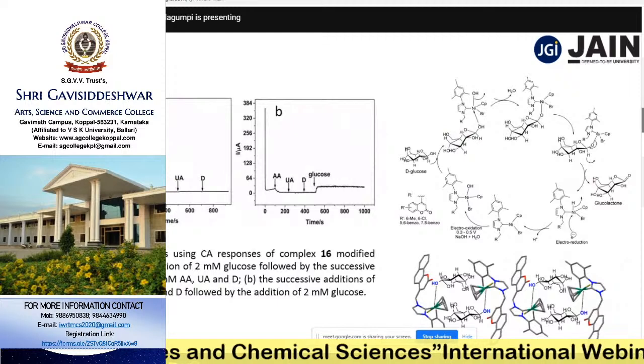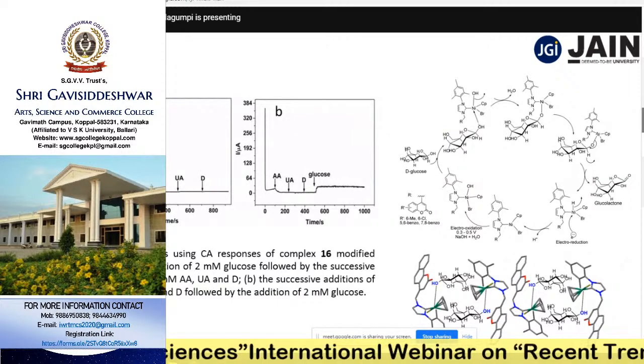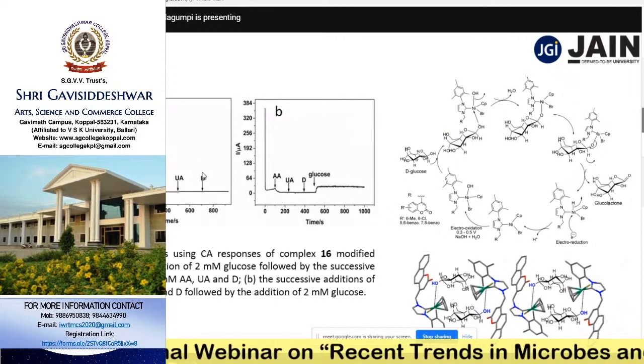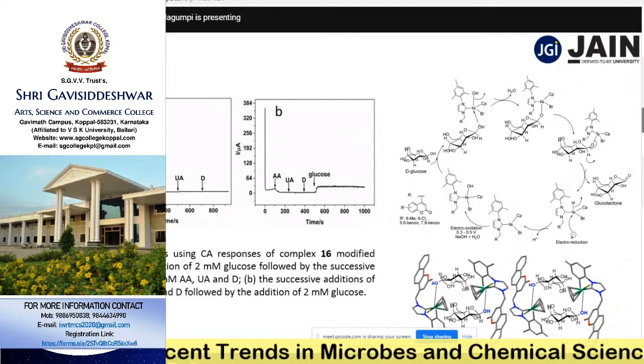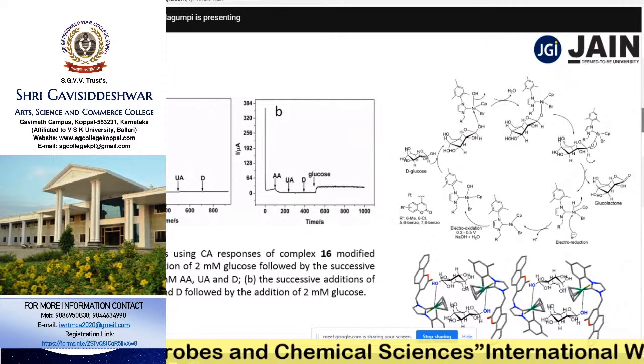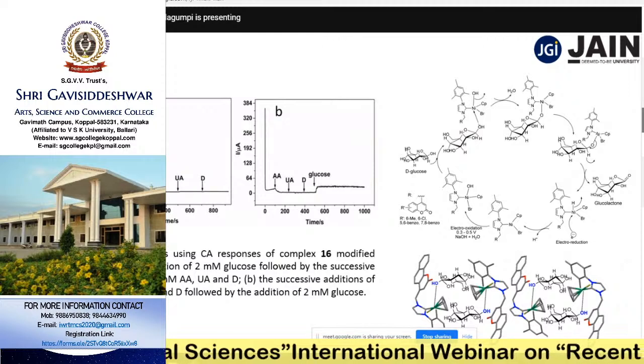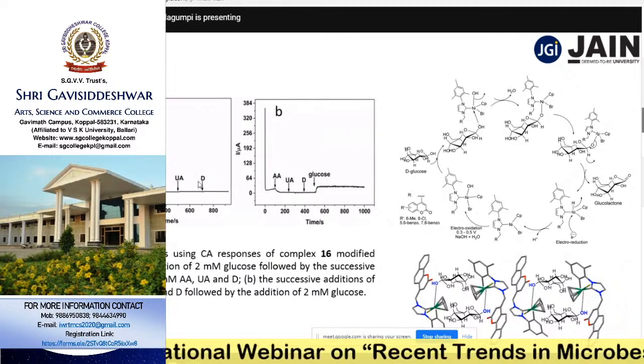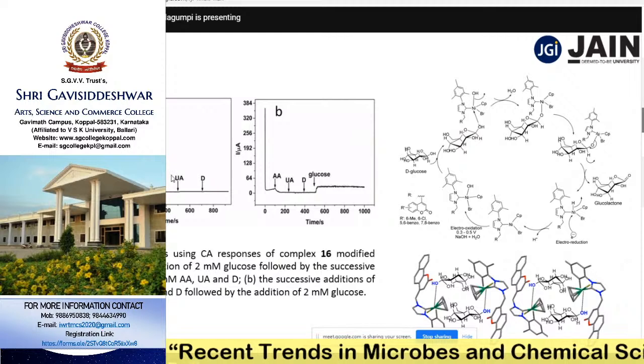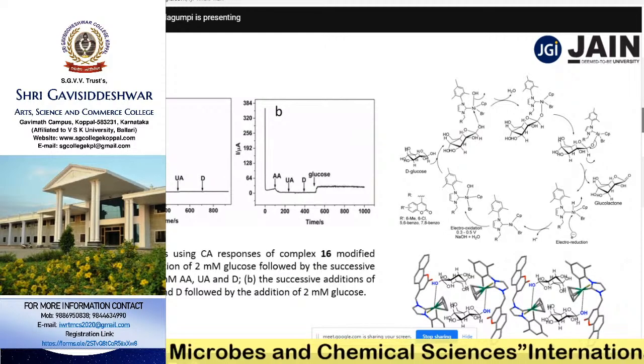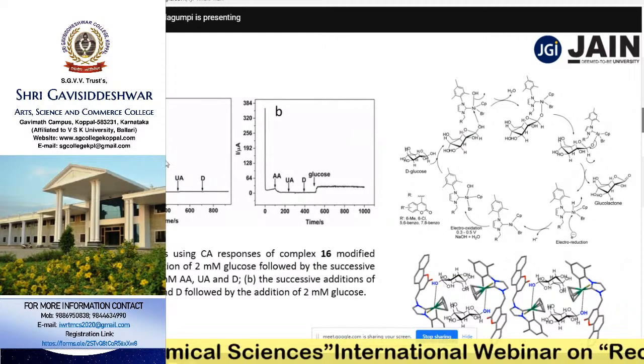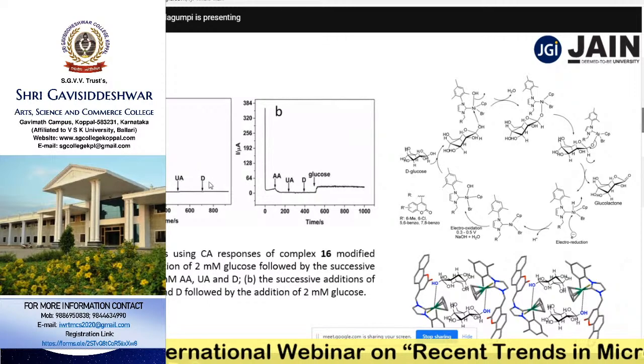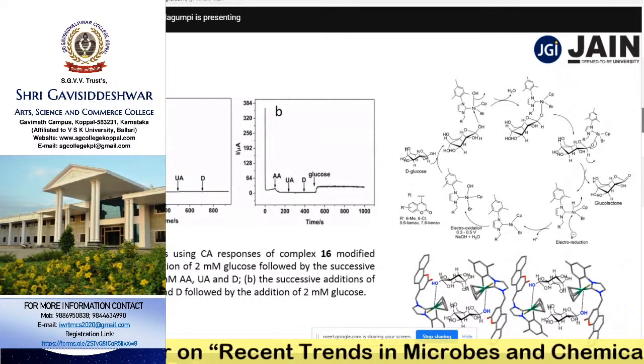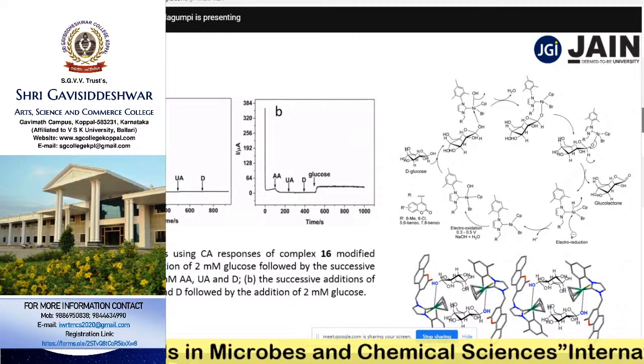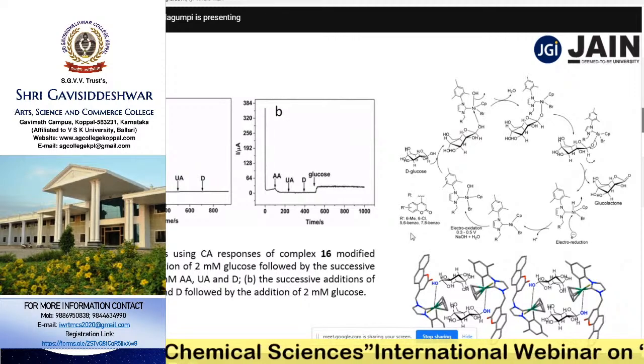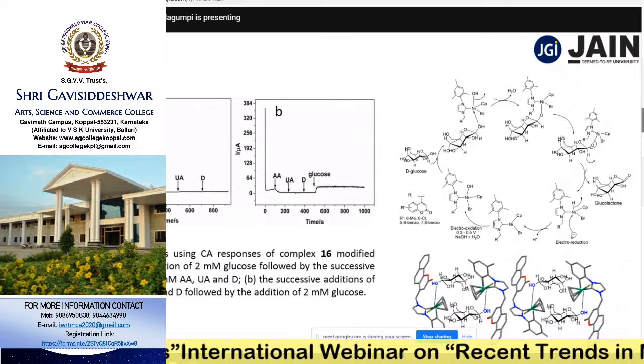Fine, we have also studied the effect of other blood constituents. Once the glucose is added, there is a response, an increase in the current. The other blood constituents, such as ascorbic acid, uric acid, and dopamine, are also present in the blood sample. But this particular sensor, the modified electrodes, has not given any response towards ascorbic acid, uric acid or dopamine. There is no response actually. But with the addition of glucose, it gives a sudden increase in the current response, which indicates that these complexes are actually glucose sensitive.